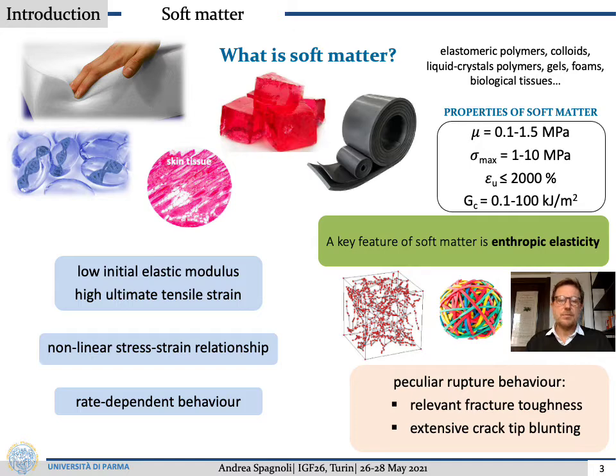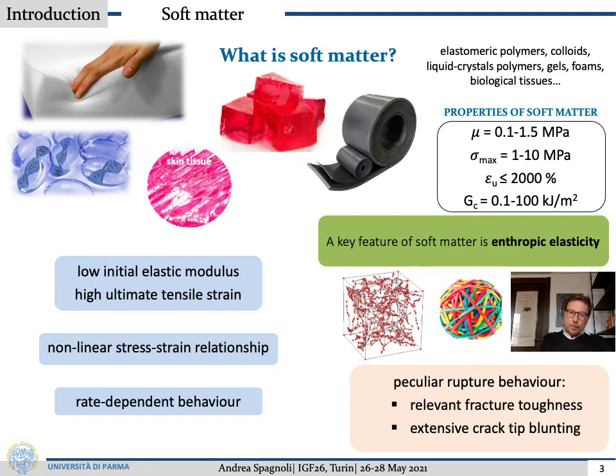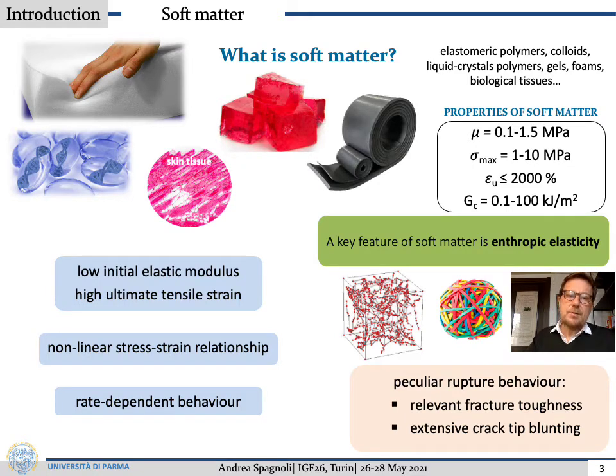When we look at these materials from a micro-scale point of view, they have the characteristic of long molecular chains. In this regard, it is very important to consider entropic elasticity, as you will see at the end of this talk. These soft materials, generally speaking, present a very peculiar behavior with a high fracture toughness and a significant crack blunting.